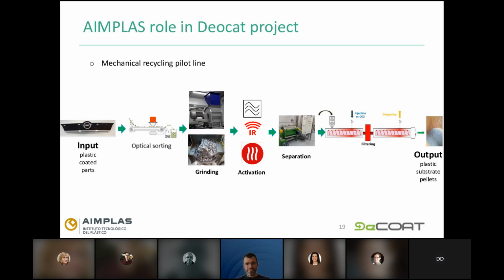This plastic substrate material will be further reprocessed in an innovative extrusion technology that will allow for melt filtration of these plastic particles, and also further remove the volatile content remaining in these plastic materials, so that at the end of this mechanical recycling method, we will be able to obtain thermoplastic pellets with improved quality that can be reused in the original application, enhancing the performance of these specialty materials developed, and also reinforcing the circular loop objectives